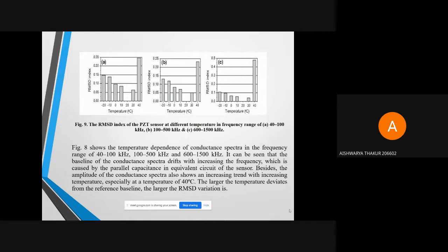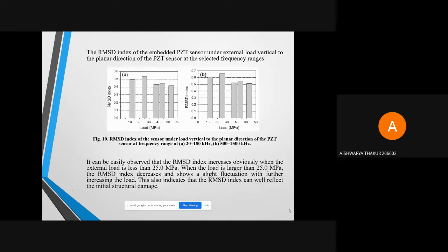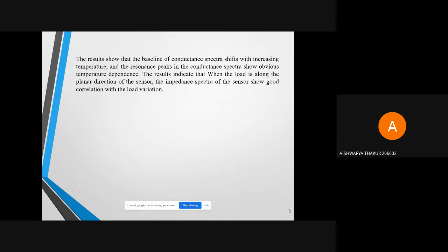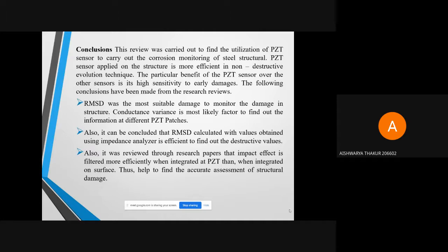It was found that the larger the temperature deviates from the reference baseline, the larger the RMSD variation. The result shows that the baseline of conductance spectra shifts with increasing temperature, and resonance peaks in the conductance spectra show obvious temperature dependence. These are the conclusions.